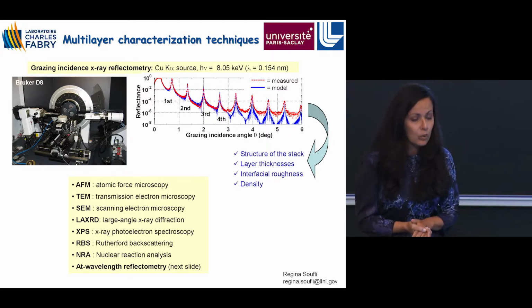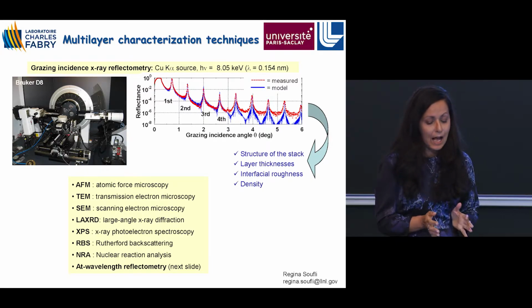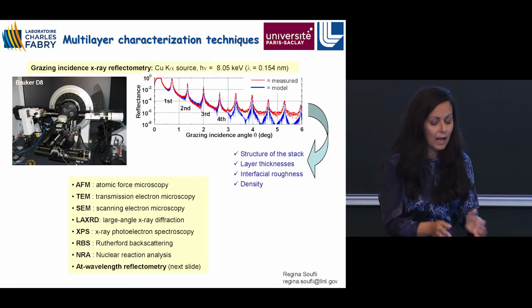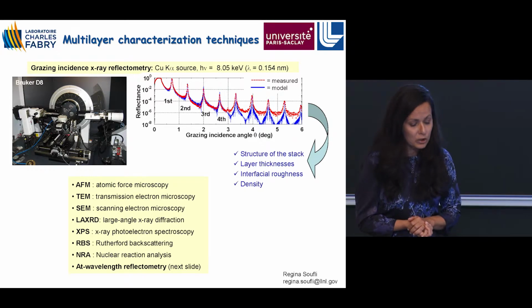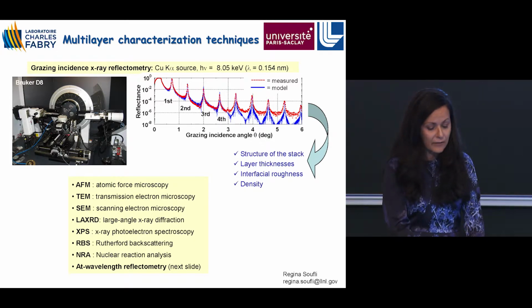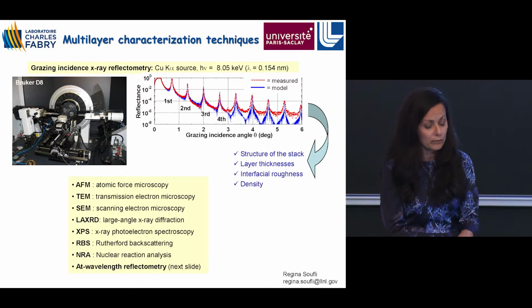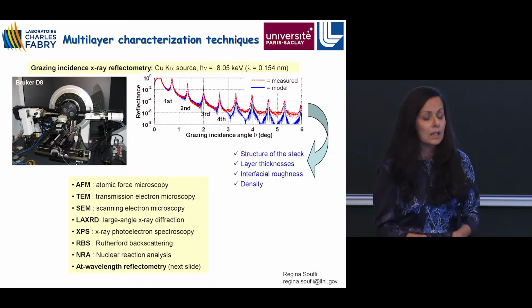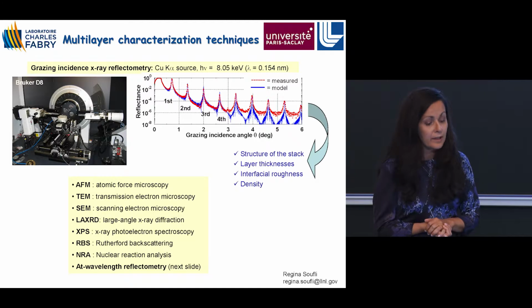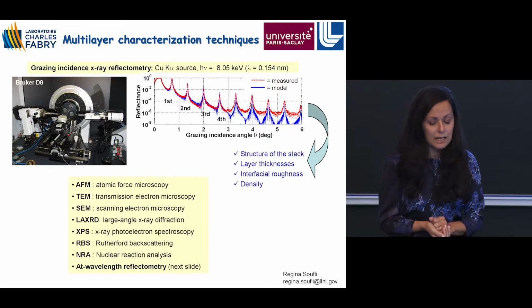So again, a few words about our characterization techniques. At 8 keV, using a copper K-alpha source is a basic in-house laboratory measurement, a very important measurement. We all have this system in our labs right next to our deposition systems. With this measurement, you can see the first order of the multilayer as well as higher orders. Again, in most cases, this is not the photon energy of operation of your multilayer, but you can still use it to characterize your multilayer. And from this measurement, you can determine the structure of the multilayer, the layer thicknesses, roughness at the interfaces, and density of the material. So this is one basic characterization.